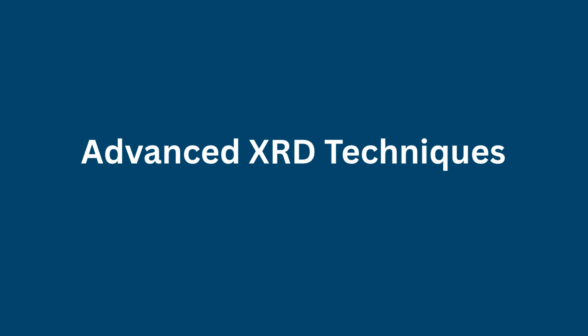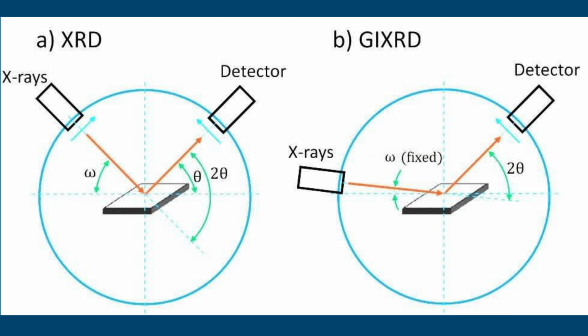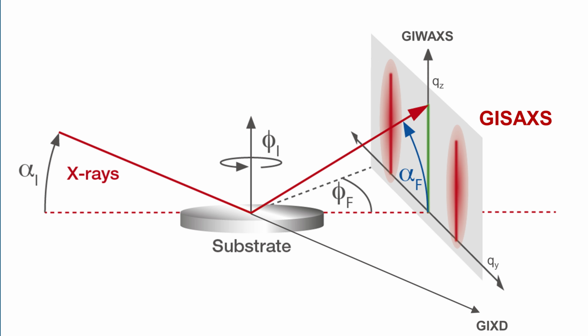Advanced XRD techniques. Recent advancements in XRD instrumentation have expanded the technique's analytical capabilities significantly. Grazing incidence X-ray diffraction, GIXRD, is particularly valuable for studying thin films, coatings, and surface layers. In this method, X-rays strike the sample at very shallow incidence angles, minimizing penetration depth and enhancing surface sensitivity. Because GIXRD is non-destructive, it is widely used for semiconductor coatings, protective films, and nanostructured materials.